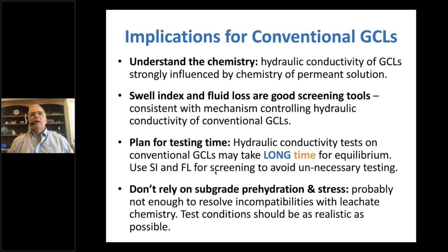As long as we've got a relationship between hydraulic conductivity and swell index for the bentonite that's in the GCL product that you're considering. Like to see at least 15 milliliters per 2 grams, over 20 would be even better. Plan for testing time. Some of these tests can take a long time. We're going to validate it, make sure it works. Use the swell index, the fluid loss, the Kolstad equation for screening to screen out products that aren't going to